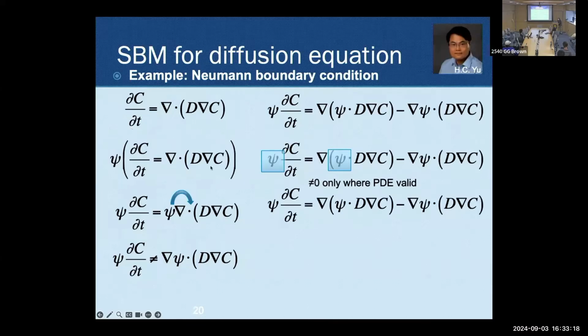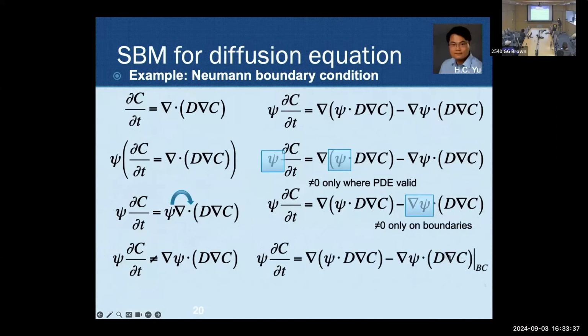Then you note this term here, grad psi. That's only non-zero on the interface, or the boundary, where the boundary condition is going to be imposed. I look at this part here and realize that you can just put the gradient of C for the boundary condition here, but also you can note that this is a flux. If you have a flux on the interface, then you can just set it to be that value. For the no flux boundary condition, this term just goes away, and if you just solve this equation, the no flux boundary condition is automatically met. That's all there is to it.